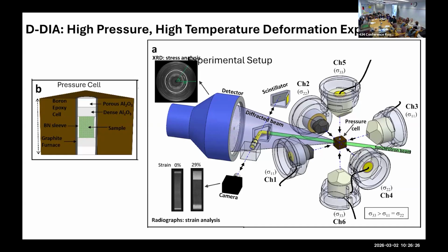And as I mentioned, you can collect diffraction and radiographs in situ. So basically you have this apparatus here, and then you have these anvils. This one here is made of sintered diamonds. The reason we use that is that it's transparent to X-rays. So on the backside, you have your synchrotron coming into this pressure cell, and then you have a diffracted beam coming out. The diffracted beam will have to go through these anvils. So we use diamond instead of tungsten carbide. I'll actually go backwards a bit and start talking about the pressure cells.